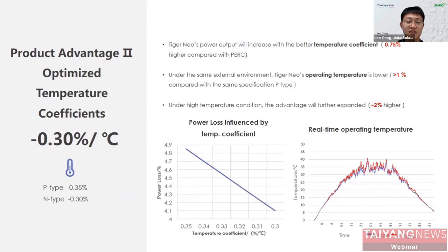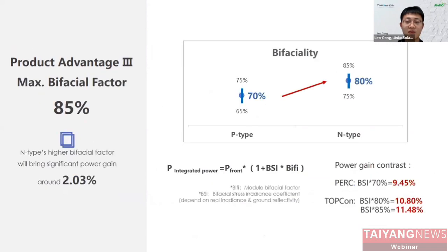As we all know, with the continuous increase in the cell size, the module current will continue to rise, and under the premise of large current modules, this advantage of temperature coefficient will continue to expand. And besides, the bifacial factor is also improved. We should be familiar that the bifacial factor of the traditional PERC module is about 70%, while the N-type cell using Topcon technology has the highest bifacial factor of 85%. As shown in the figure, using the P-type monofacial module of the same specification as a baseline,